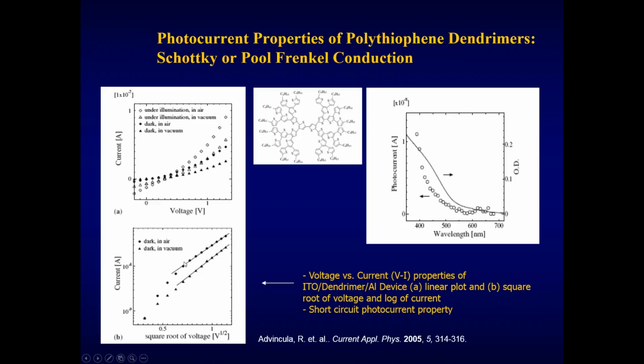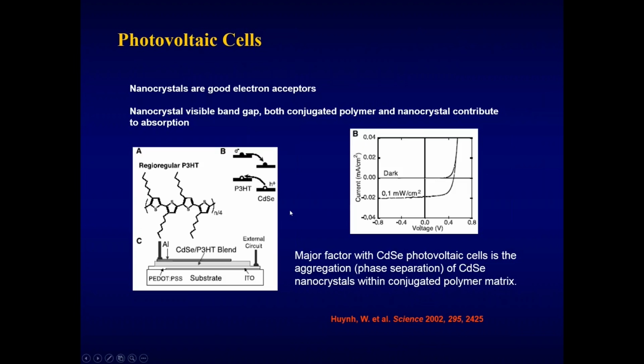We were able to characterize their fluorescence and absorption properties. And what's interesting is that the cadmium selenide, when surrounded with the polythiophene dendrons, has a quenching mechanism, which we attributed to an electron transfer between the ligand and the nanoparticle, which is interesting because this type of behavior actually makes it useful for solid-state devices such as photovoltaic devices or the photovoltaic effect, as I'll show you soon.